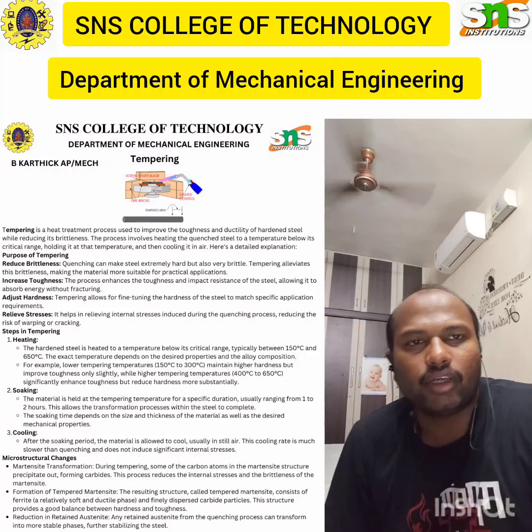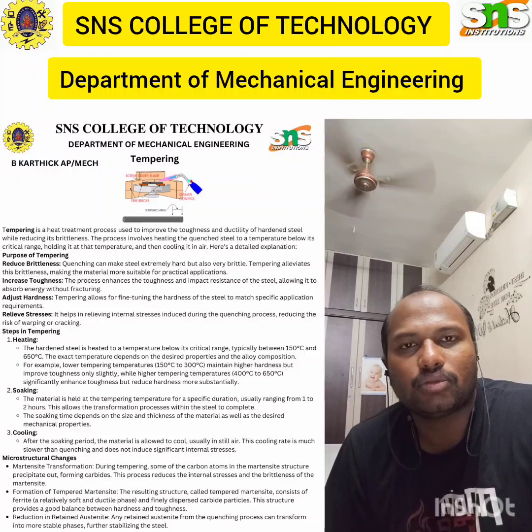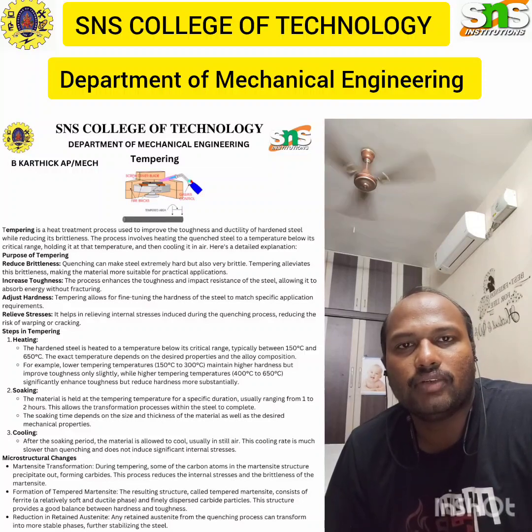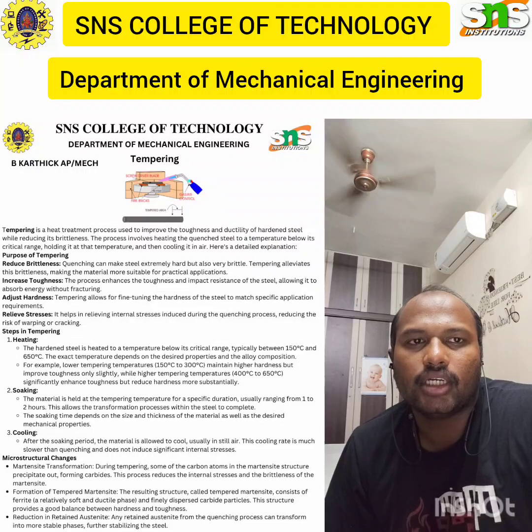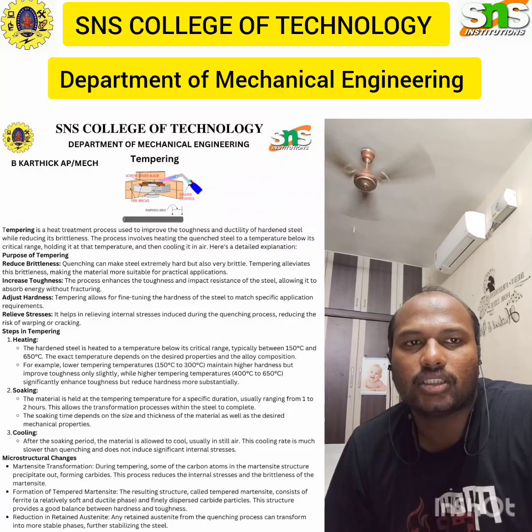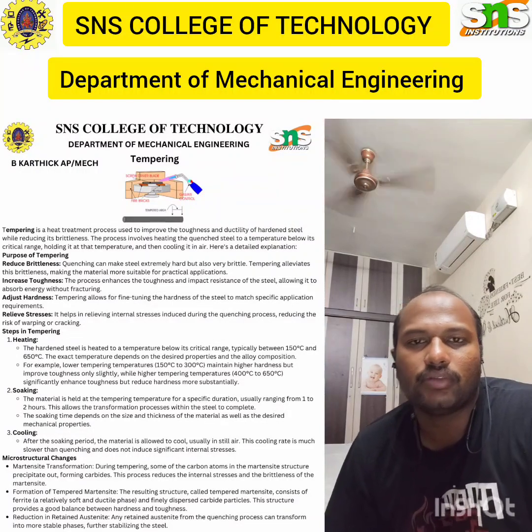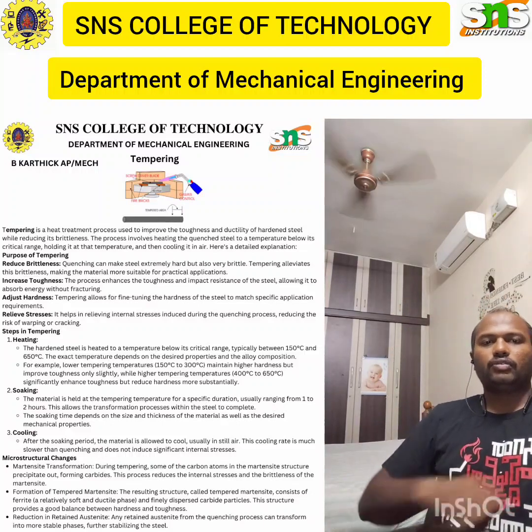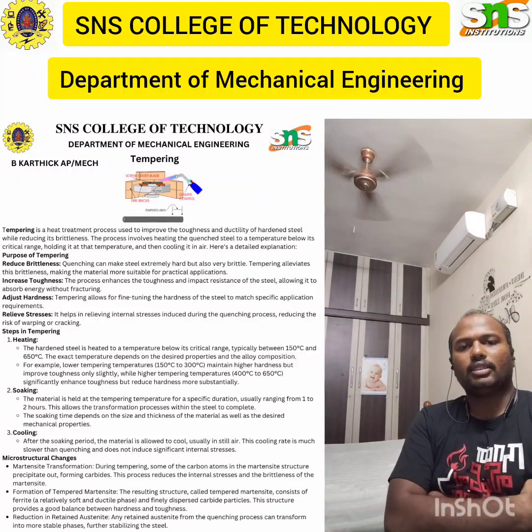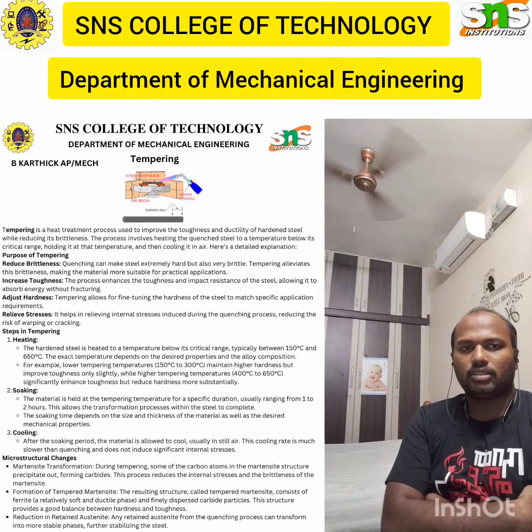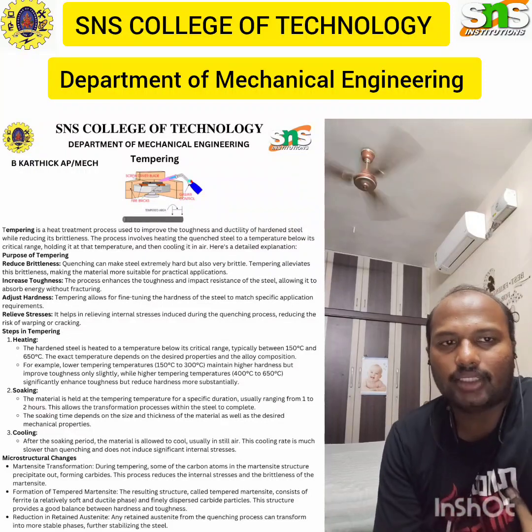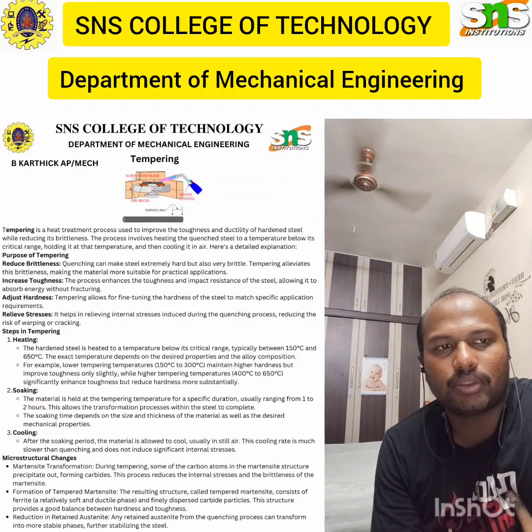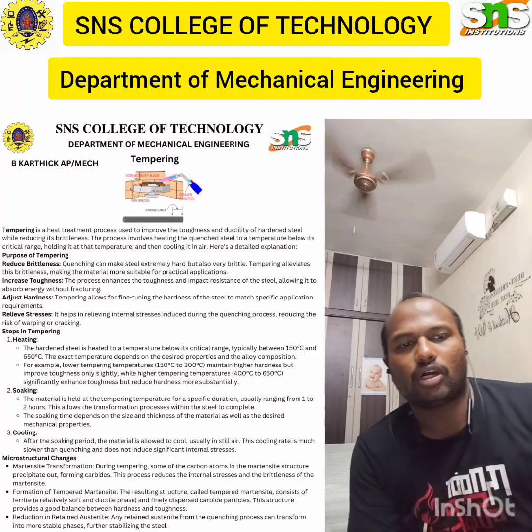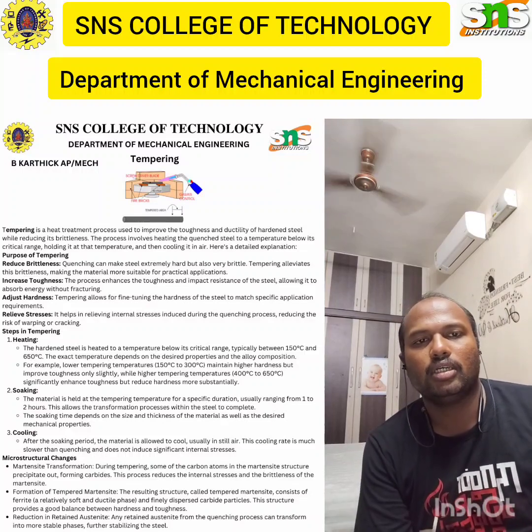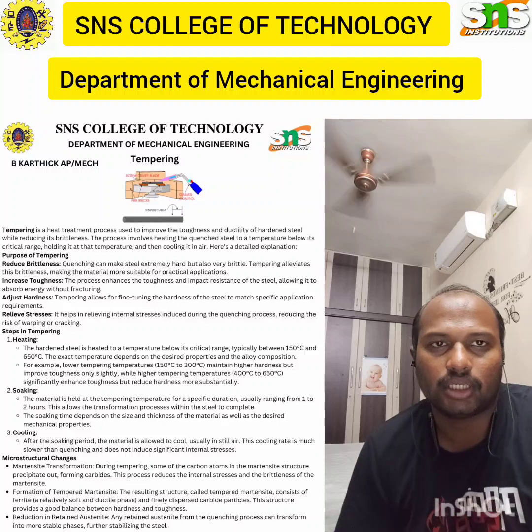Effect of tempering temperature: low temperature tempering, 150 to 300, produces a steel with high hardness and moderate toughness, typically used for cutting tools and wear resistance applications. Medium temperature tempering, 300 to 450 degrees Celsius, results in a good balance of hardness and toughness, commonly used for springs, hand tools and certain machine parts. High temperature tempering provides maximum toughness and ductility at the expense of some hardness, suitable for components like automobile parts, structural components and heavy duty machinery parts.